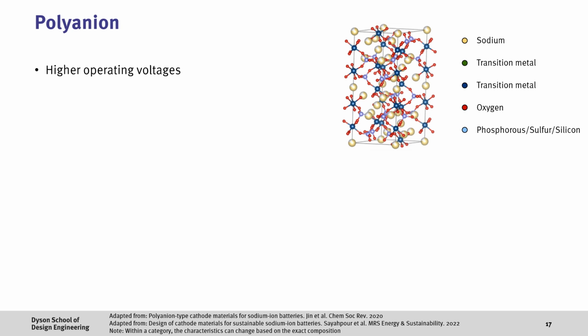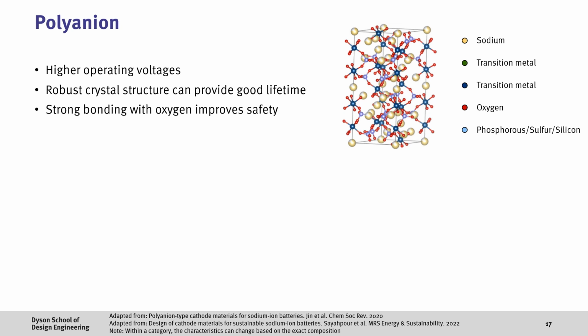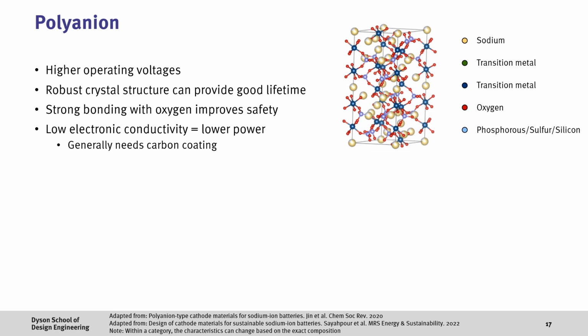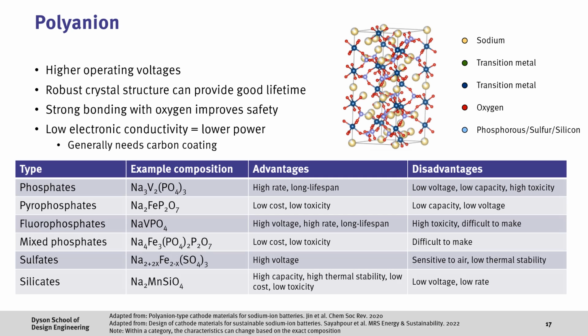Finally, we have the polyanion family of materials which generally have higher operating voltages than other materials. Their robust crystal structure can provide good lifetime, and the strong bonding with the oxygen in the structure improves their safety characteristics. However, the specific capacity is generally lower than metal oxides, and their low electronic conductivity usually means they need to be carbon coated. Here, there are a number of different types of material, each with their pros and cons, including phosphates, pyrophosphates, fluorophosphates, mixed phosphates, sulfates, and silicates.